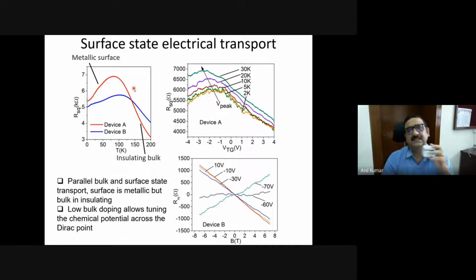If that is the case, what happens at very low temperatures, and if you start increasing the temperature, what you're measuring is the metallic surface state, because it's metal. So as you increase the temperature for a metallic material, the resistance increases, and keeps on increasing. At the same time, the bulk of this material is insulating, or a semiconductor with around 300 meV band gap. The resistance of that semiconductor keeps on increasing when you go from high temperature to low temperature.